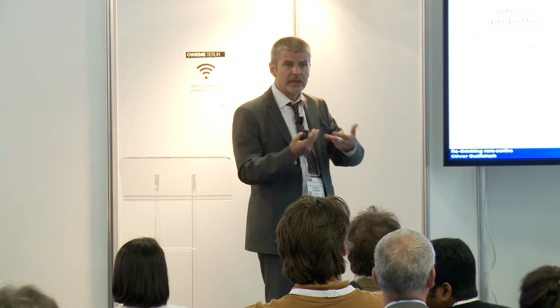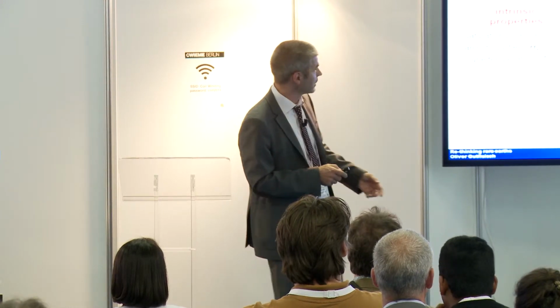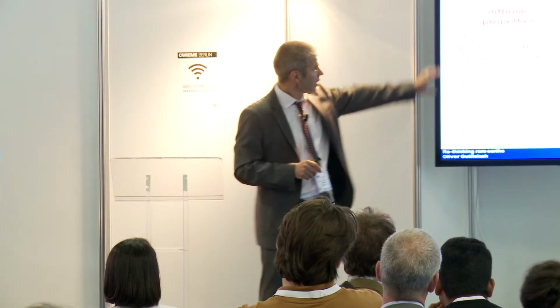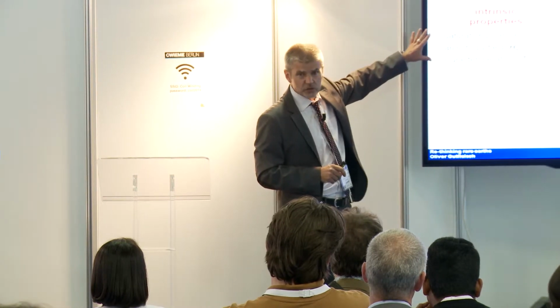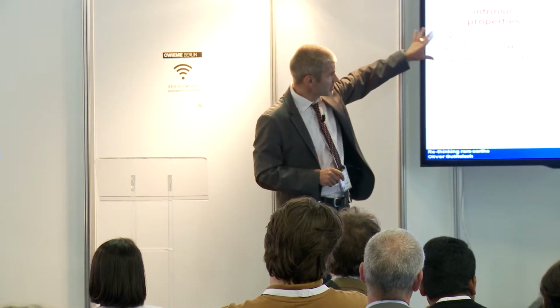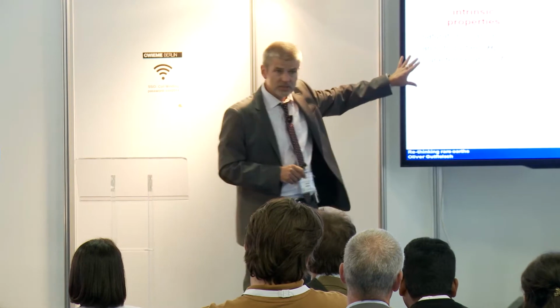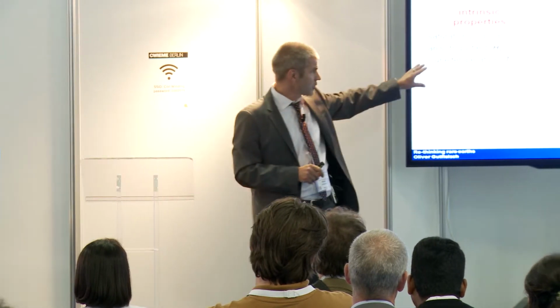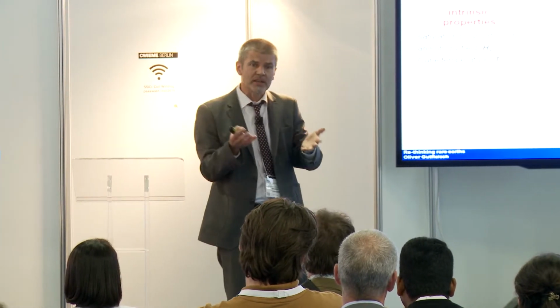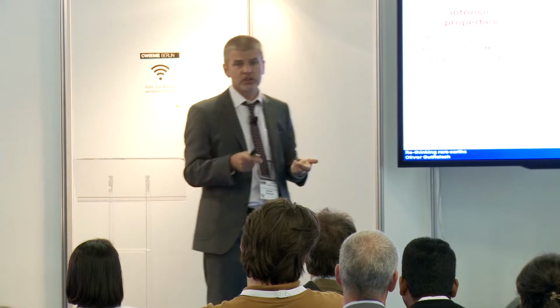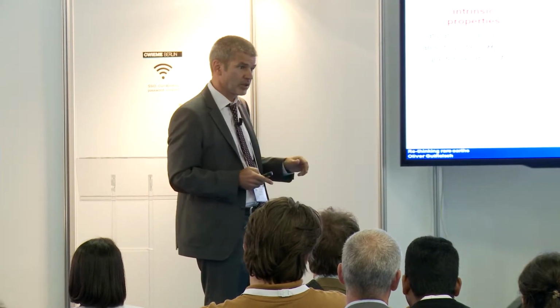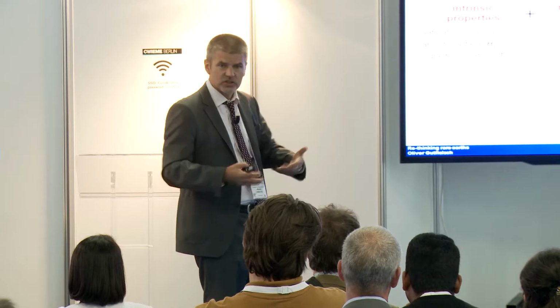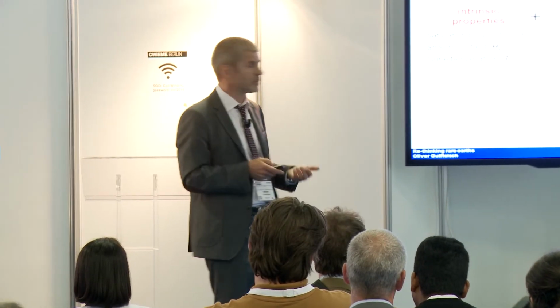So how do we actually make a good magnet? For a good magnet, we have an intermetallic compound. It has very good intrinsic magnetic properties: the saturation magnetization, the anisotropy field, and the Curie temperature. These are our theoretical upper limits to what we can in principle achieve. This needs to be thermodynamically stable, which means it doesn't decompose immediately or at elevated temperatures.